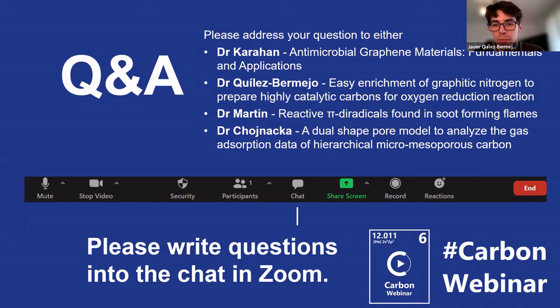Thank you for the question. The textural properties, the structure of the carbon material, are almost as important as the type of nitrogen you have in your material. But to my mind, if you don't have an active site, the structure or everything else is not as important. You need some nitrogen or some heteroatom defects, something that can disturb the electronic structure of the carbon material in order to make the chemisorption of the oxygen molecules easier. But the carbon nanotubes have a different hybridization of the carbon atoms, which can also increase the catalytic activity. Have people tried? Yes, there are people who have tried nitrogen doping on carbon nanotubes, and the catalytic results are quite good.